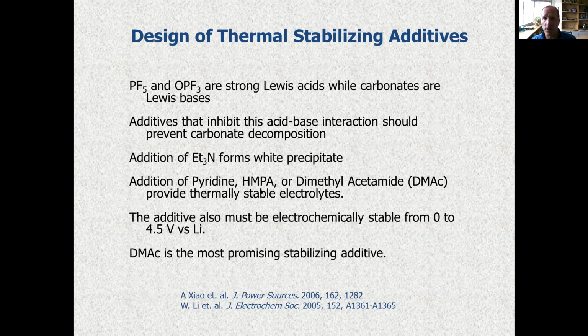However, pyridine or HMPA or dimethylacetamide provide very good thermally stable electrolytes. However, the additive must also be electrochemically stable. And of these solvents that were investigated, dimethylacetamide is really the most promising electrolyte additive, and this is an electrolyte additive that has been incorporated into commercial cells.